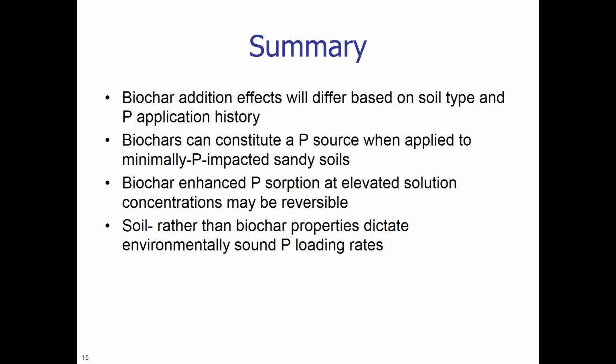So we come now to a summary of what we have seen and learned so far. Biochar addition effects will differ based on soil type and the P application history. Biochars can constitute a P source when applied to minimally P-impacted sandy soils. Biochar enhanced P sorption at elevated solution concentrations, but that may be reversible, and it's soil rather than biochar properties that dictate environmentally sound P loading rates, that is at the lower concentrations.